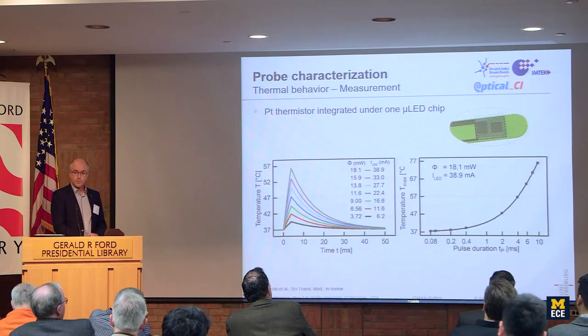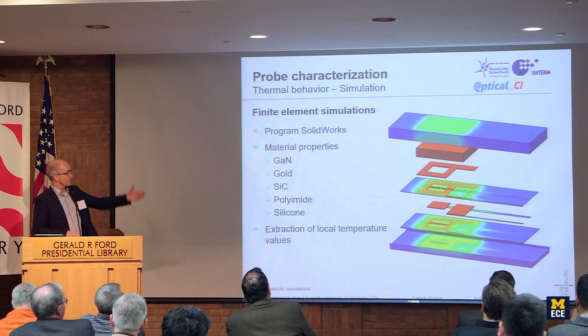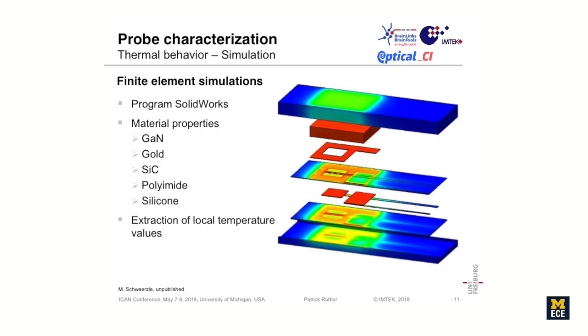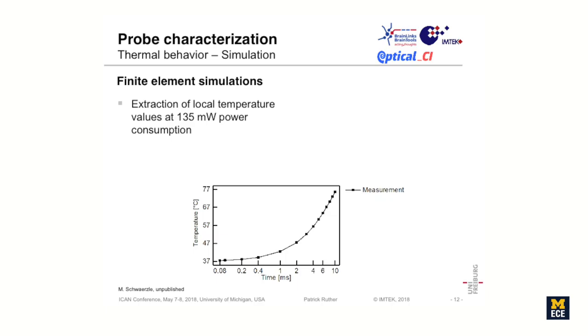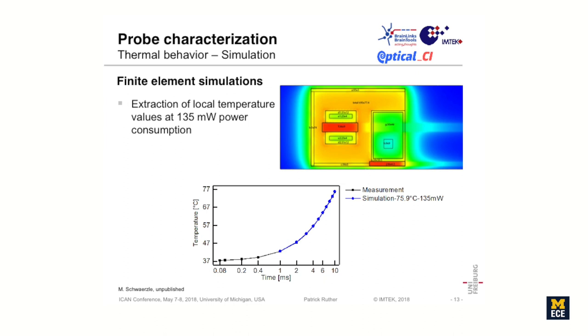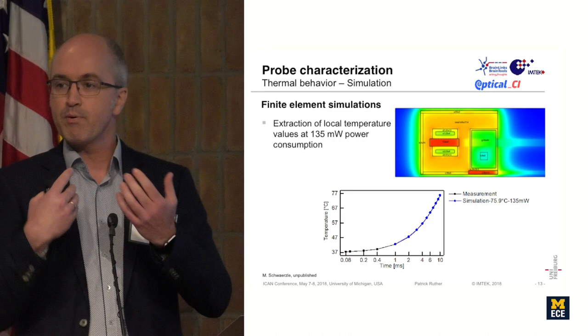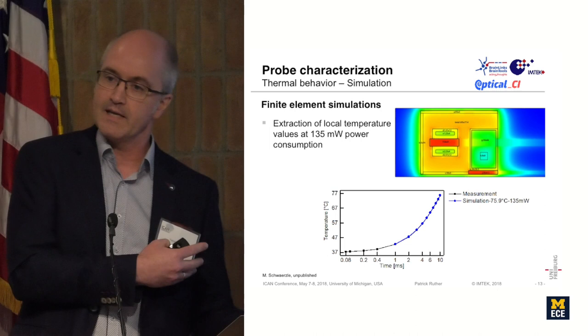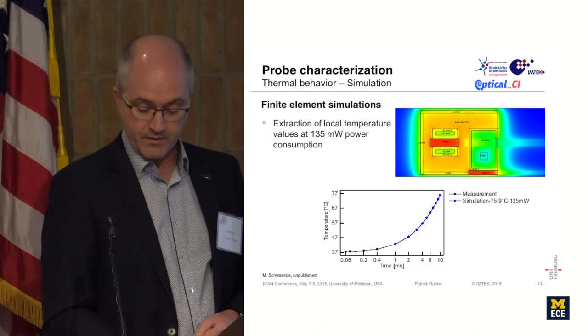So what we had to do is simulate the entire system. This shows an explosion view of what we did. This is the LED, this is the metal tracks that we have, these are the bond pads, and the encapsulation of the entire probe, and then looking at the temperature over the device as a function of the different materials and their respective properties. Now, coming back to this measurement and putting a simulation over it, I didn't believe that at the beginning because they perfectly match. Obviously, we have the right set of parameters. If you play around with that a bit, you shift by plus minus 5 degrees, but I would say this is good enough for looking at the temperature development in the probe itself.